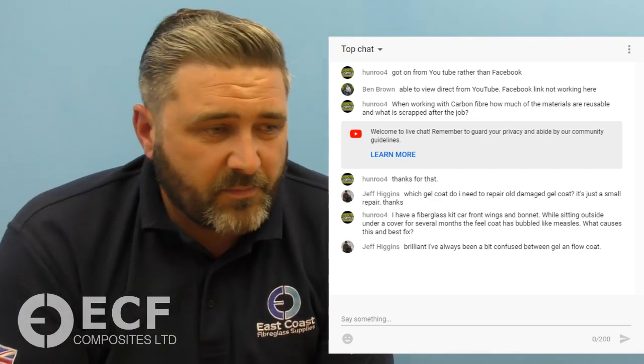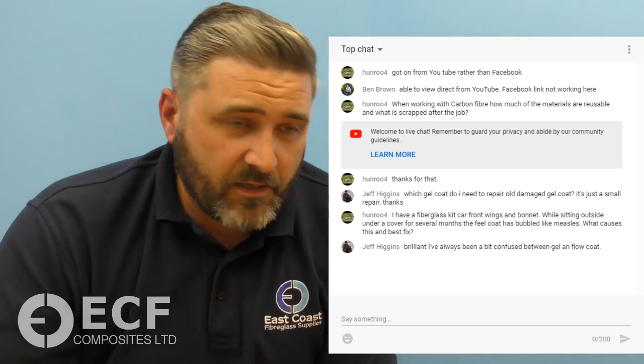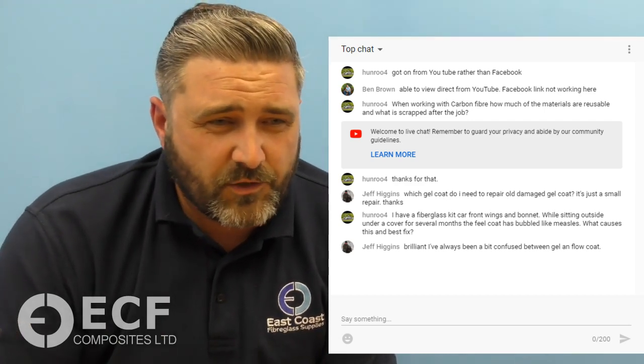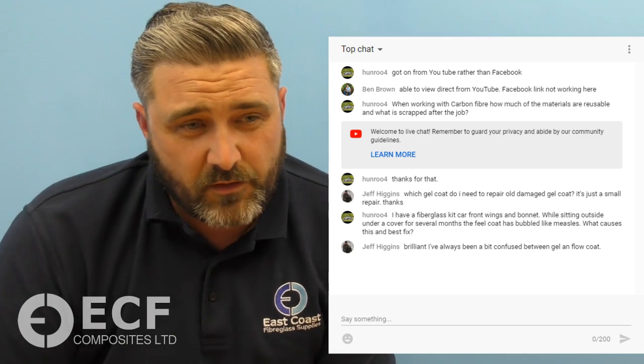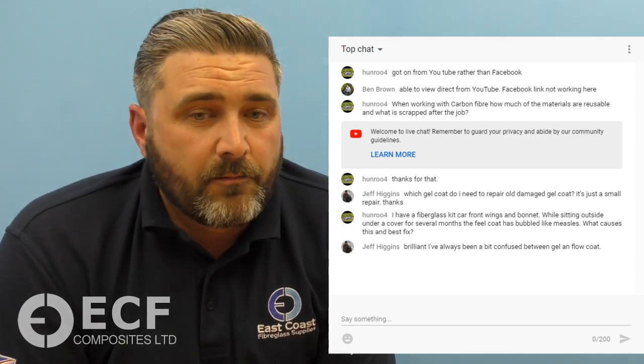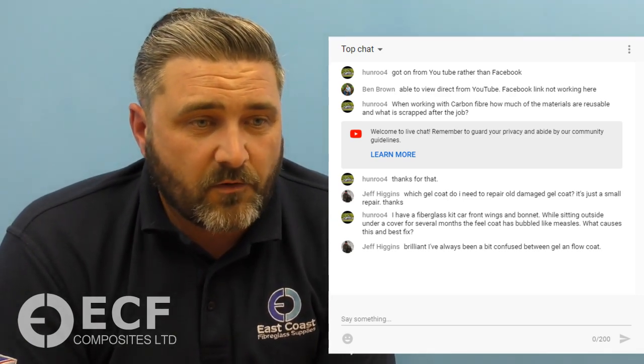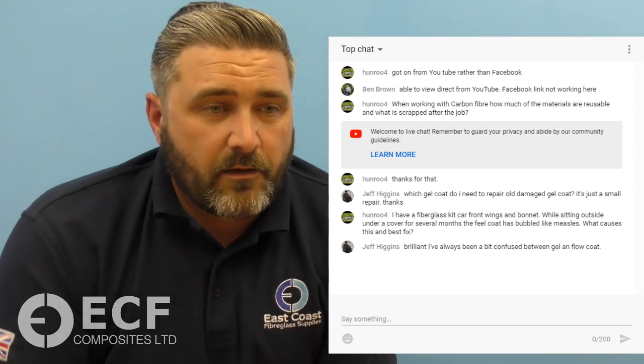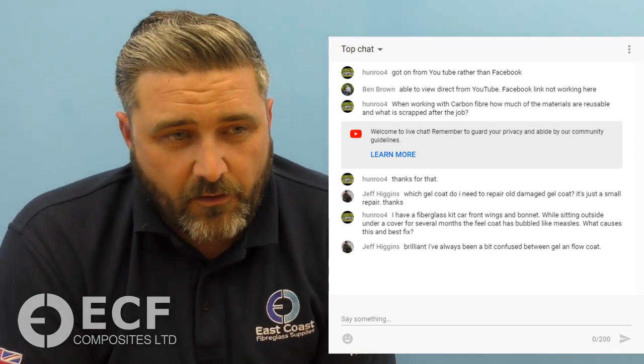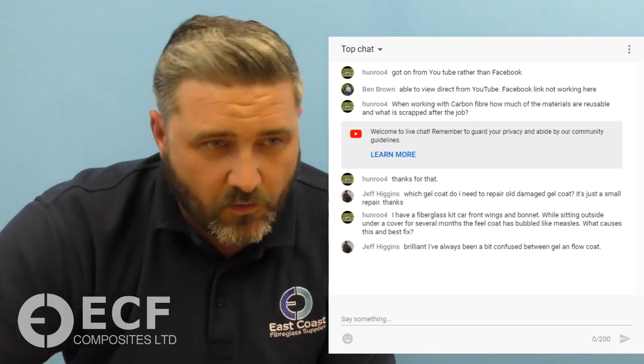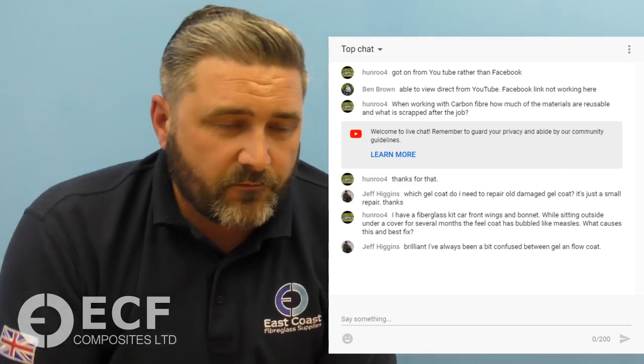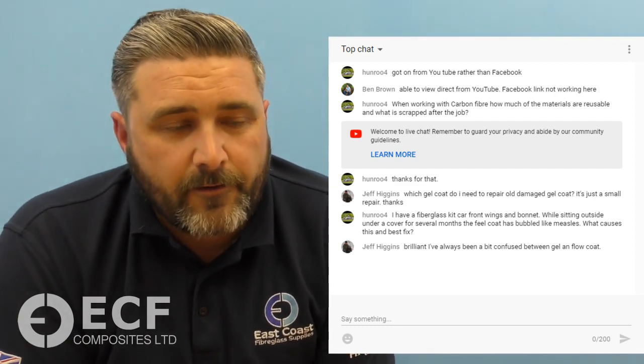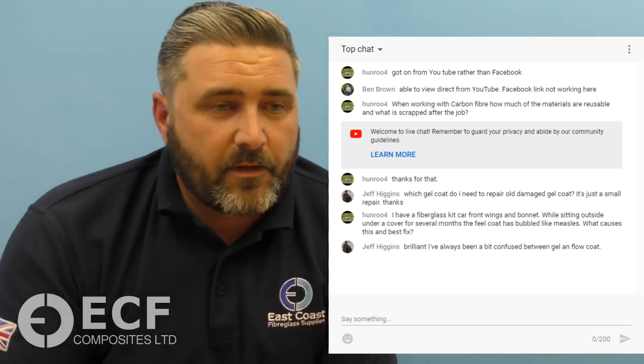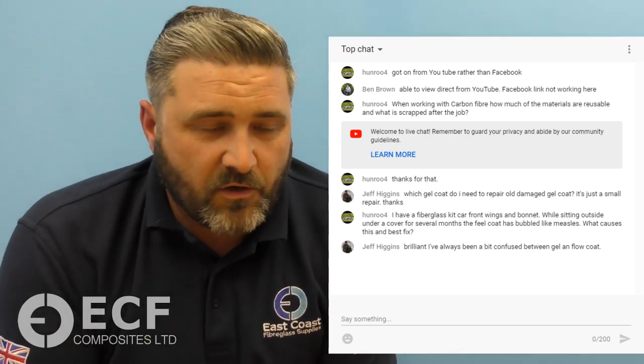Or if it's a big area, you can skim it over, but rather than use gel coat like they do with boats, use epoxy. So mix something like West Systems 407 with an epoxy, make a fairing compound, skim it over, sand it all back, few more coats of epoxy over the top of that, flat that back, and then you just finish it off with an automotive paint.